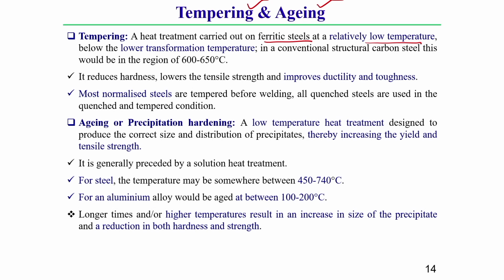Here the temperature is below the lower transformation temperature or lower critical temperature. In a conventional carbon steel structure, this would be within a range of around 600 to 650 degrees centigrade. This you should keep in mind. Due to this tempering, hardness is reduced and tensile strength is also reduced, but the tempering operation improves ductility and toughness.